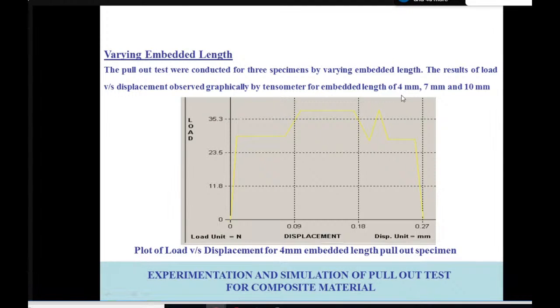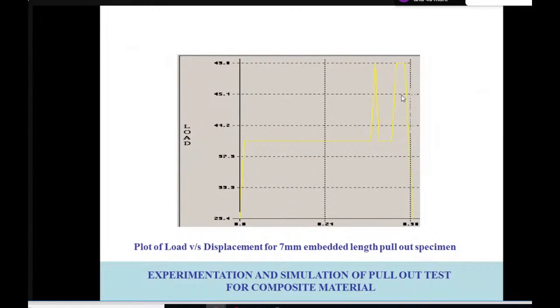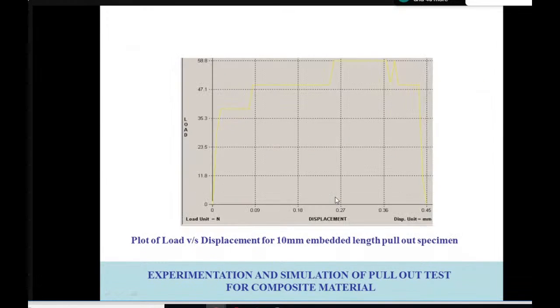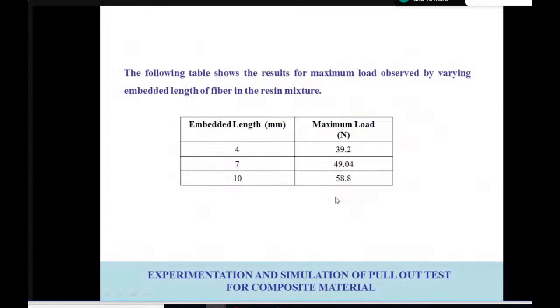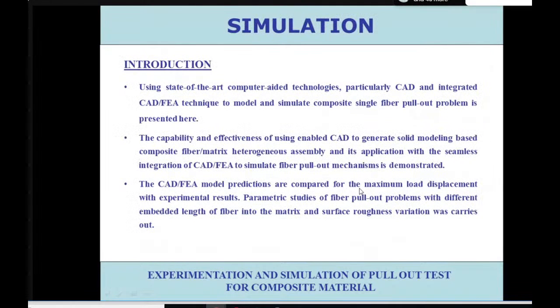So interface surfaces are being increased by this embedment length. Now, if you increase the interface length, then what happens to 7 mm, 10 mm, and 4 mm? From the results you can see that for 4 mm the load required is 39, for 7 mm 49, and for 10 mm 58.8. So basically this gives you an idea that if you take the fiber and matrix, whatever contact area you give between the fiber and matrix for bonding, accordingly the strength will vary.